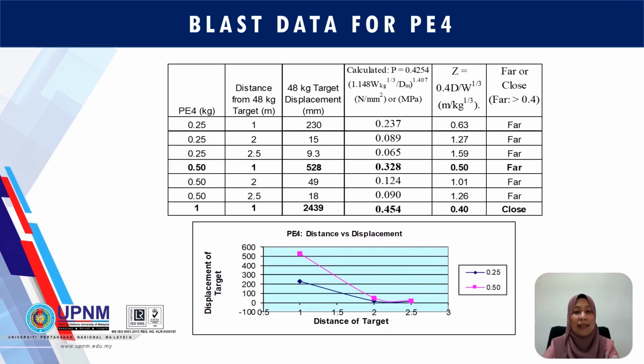Okay, now from the tables and graph that I've shown just now, we can see the normal trend of high pressure due to explosion at closer distance, and there is a drastic reduction when the explosion is moved further away. So even though most of the tests are classified as far detonations, we can see that when the Z value is closer to 0.4, for example 0.5, the displacement of the target is big. So this shows the validity of the Z value as an indicator of high impact area.